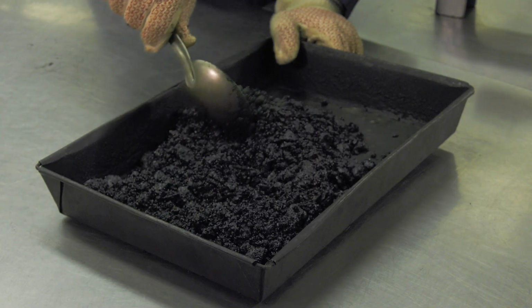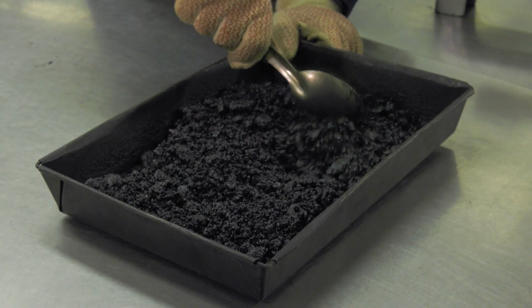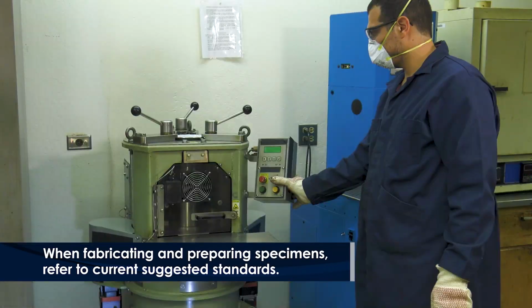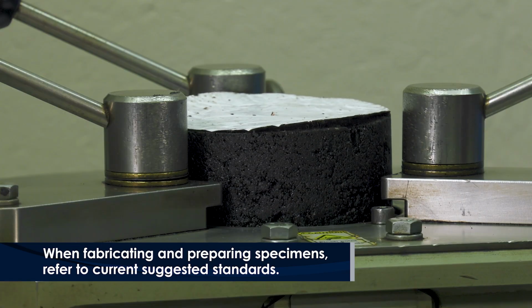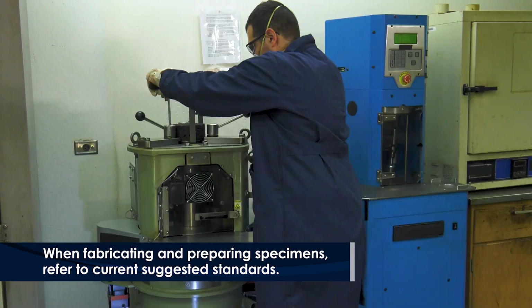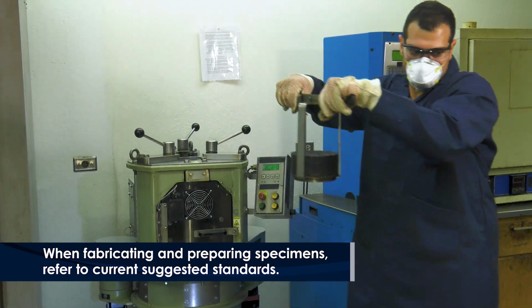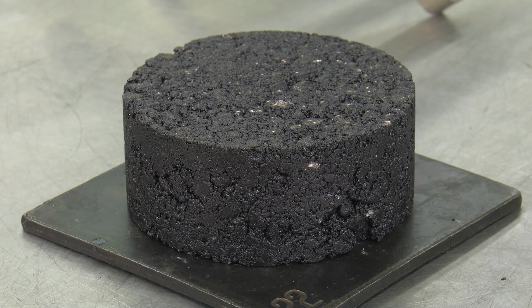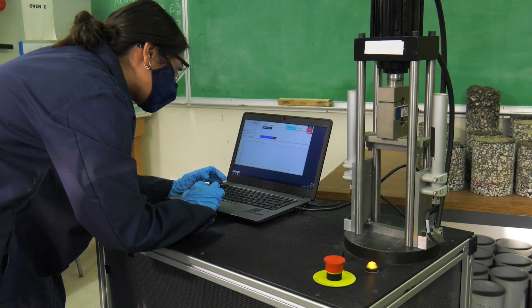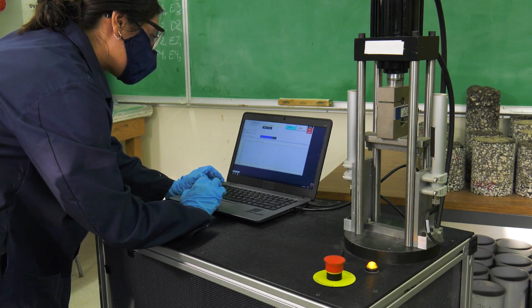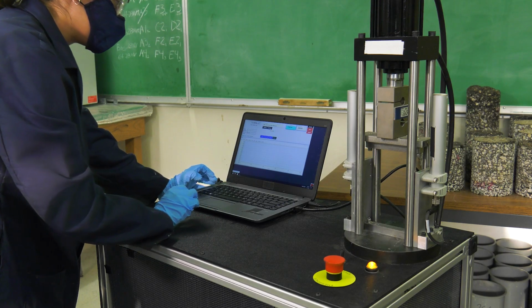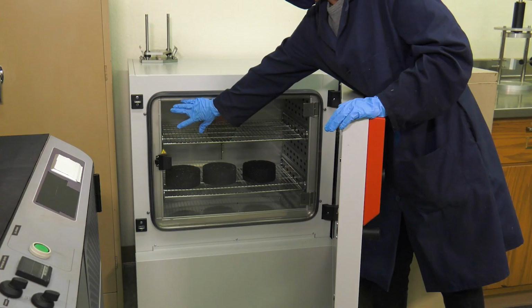For laboratory-prepared specimens, short-term condition the asphalt mixture according to AASHTO R30 and fabricate 3 150 mm diameter specimens at the target air void and target height using a superpave gyratory compactor, or SGC. Allow the specimens to cool. Determine the test temperature based on the climatic intermediate performance grade temperature as described in the standard.